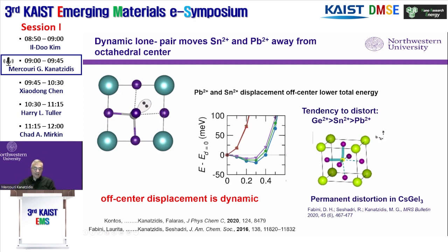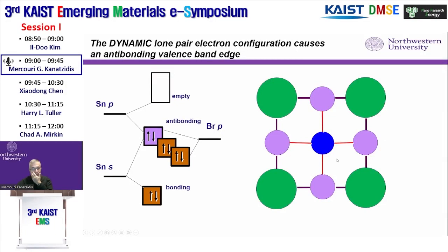So this is a dynamic effect because it doesn't settle in one place when it goes off-center, except in germanium. In germanium, because the tendency is so strong, the lone pair wins the competition. And so the germanium goes to one side, becomes ordered, the symmetry gets lower, and you have a totally distorted structure. And the germanium systems are not as interesting from the optoelectronic point of view. So this off-centering is key.